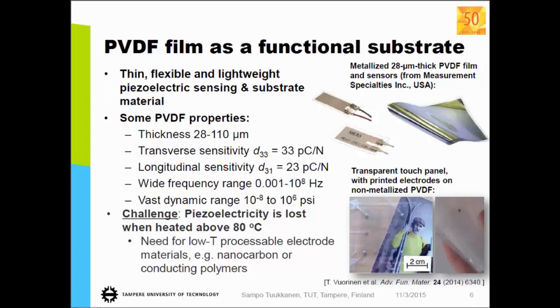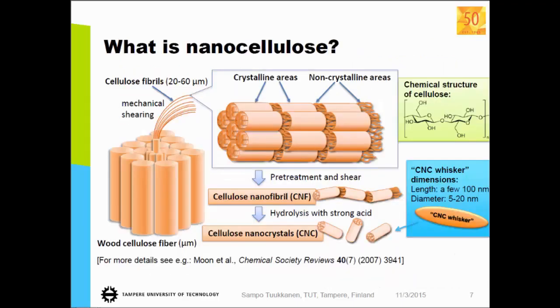Yeah, and in this case, you have this limitation of 80 degrees, so you destroy the piezoelectricity if you sinter the device at high temperatures. So this is why we selected this kind of conducting polymer nanocarbon ink for this application.